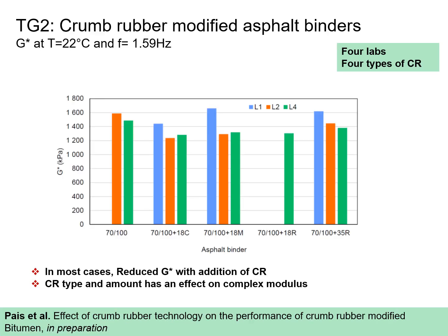An example of the work of TG2 on crumb rubber modified asphalt binders is shown here. In this case, we had 4 labs involved and 4 types of crumb rubber were looked at. Again, you'll see complex modulus values for different binders, the 70/100 binder and the 70/100 binder blended with 3 types of rubber and 2 amounts of rubber. In most cases, you see that there is a reduction of the complex modulus with the addition of crumb rubber. And as is seen here, the type and the amount has an effect on the complex modulus.